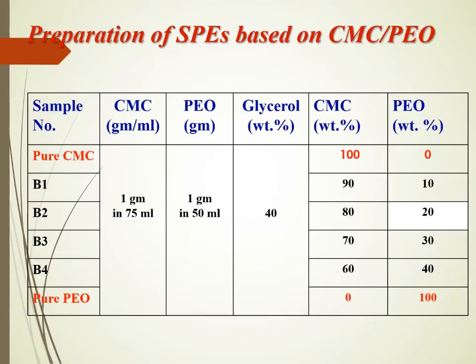Sample preparation. The solution casting method was used to prepare our solid polymer electrolyte materials based on CMC and PEO, where pure CMC was prepared by dissolving 1 gram of CMC in 75 milliliters of distilled water, and a constant weight percentage of glycerol was added to enhance the mechanical properties of the prepared films. Also, the bulk solution of pure PEO was prepared by dissolving 1 gram of PEO in 50 milliliters of distilled water, and the same percentage of glycerol was added. Hence different concentrations of CMC and PEO were mixed with each other, and we obtained the blended CMC/PEO solid polymer electrolyte materials as presented in the table.